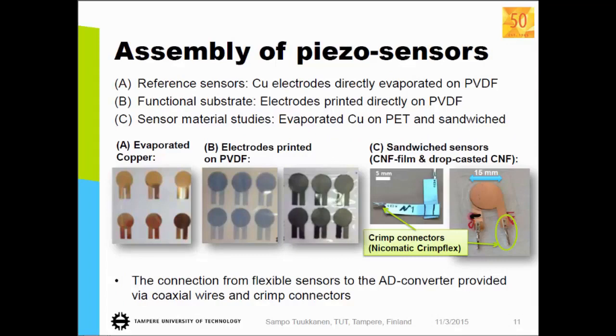And then for this paper, actually we have fabricated these single sensor elements, which are used to study how well the electrode materials work together with the sensing material. So we have reference sensors made on PVDF by evaporating copper on it, and then similar structures where we use the printed electrode. So these have both sides with the electrodes on top of each other in this area, and the contacts have to be in different positions so that you get contacts. And then if we want to study a new sensing material itself, we can also use this kind of sandwich structure, putting electrodes, just pressing them on both sides.